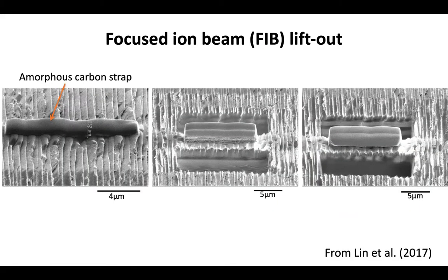So we wanted to understand what was responsible for the blazed diffraction grating on this quartz crystal. And again, we did some focused ion beam analyses where we dug a trench into one of these ridge faces right here, and extracted a sample for analysis by transmission electron microscopy. So now again, we're looking at this face in cross-section, and you will see, if I can find my arrow, this blazed diffraction grating, which is fairly periodic here. And when we look at it in cross-section, we find boundaries that are separating these layers. The C-axis of the quartz crystal is indicated as follows. And I have a lot of experience in working with quartz, and I knew immediately that this had to be a certain type of what is called a twin of quartz, known as a Brazil twin.